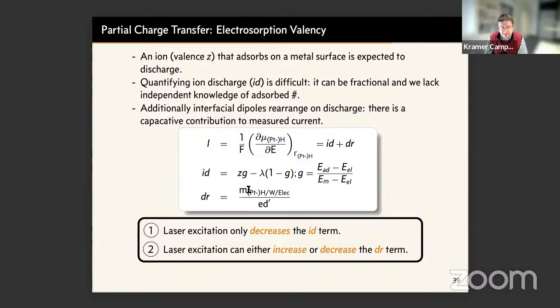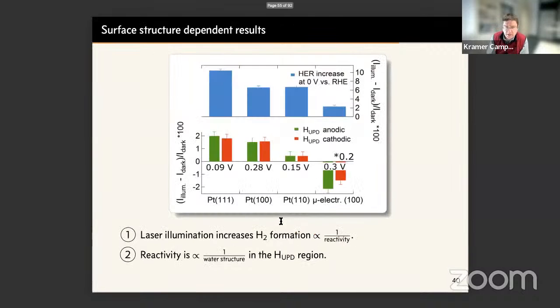If you dig into this ion discharge term, you have this valence, this extent of discharge lambda, and then this G term, which is this potential gradient across the double layer compared to that across this adsorbate. And the critical point to note is that the laser excitation only decreases this ion discharge term, right? The population of this antibonding orbital can only make this thing smaller. Of course, we have no idea how the solvent dipoles respond from this measurement, so it can either increase or decrease this dipole relaxation term.